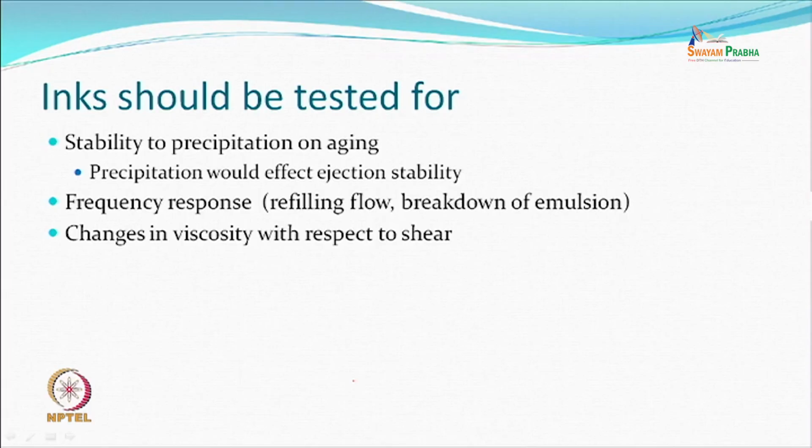These inks will obviously be tested for stability to precipitation on aging. Then frequency response. Whether you have continuous jet printing or drop on demand, the frequency is different. When you talk about kilohertz, you understand what it means: in such a small time, you are ejecting so fast.